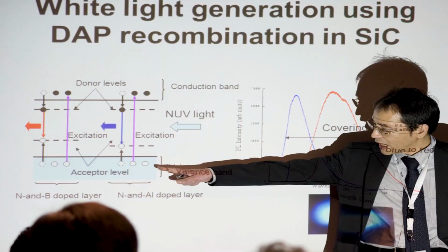And the unique feature here is that there are broad curves, and then it comes out in the visible region if you're doing this in 6H silicon carbide. And for that, he needed thick layers of silicon carbide. So I was, oh yes, yahoo! I have a method. So then I started collaboration with this prestigious group at Meijo University.